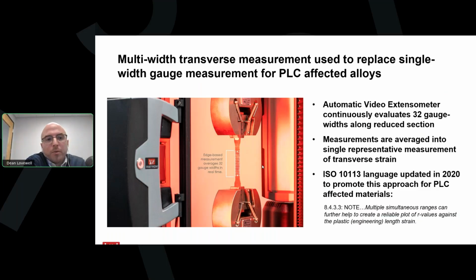So the question that we asked ourselves was, how could we include the width strain behavior all along the reduced section so that we'd not only get a smoother transverse strain curve, but we'd also get more representative R values that would be more repeatable test to test, lab to lab. The solution we developed was a video extensometer that instead of tracking just one gauge width, actually tracks 32 gauge widths along the specimen. So this captures the width strain behavior wherever it happens within the gauge length, and it averages the result into a single value. This Instron developed technology called AVE3 and this approach is accepted both by ISO and ASTM. And the most recent version of 10113 was actually published with language recommending this approach as a way to obtain more reliable characterization of R value.